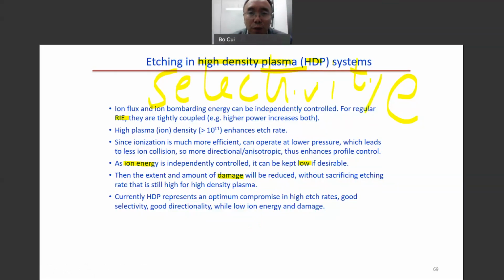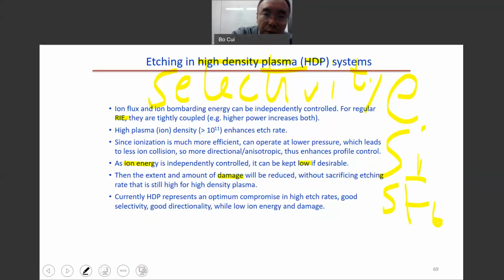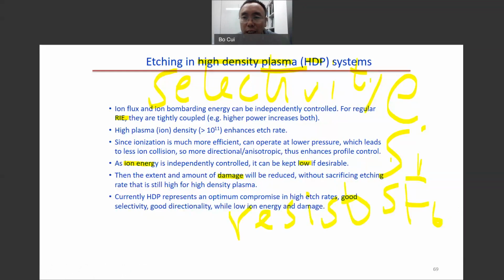Selectivity is also higher. When we have a lower ion energy, the physical bombardment is less, so the chemical reaction is more. We know that for the chemical reaction, you can have very selective etching. That means the etching rate of different materials can be very, very different. For example, if we want to etch silicon using SF6 gas, and the mask can be resist, then when we use the resist as the etching mask to etch silicon using SF6 gas, the selectivity can be 1 to 100. Can be very high if we use a low power.